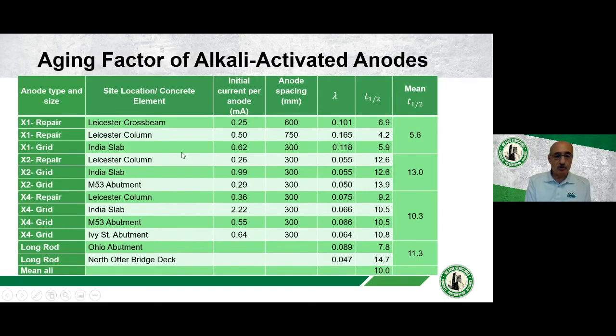Okay, I promised a table before, and this is a whole list of the structures that we have been monitoring, and we've been monitoring long enough, beyond 10 years, so that we could determine what we call the aging factor, or the half-life of each anode. This is the one that I was talking about. It's about 7 years. On the same structure, we had embedded at the same time another area which we've been monitoring, but with a spacing of 750, and you can see that increase in spacing sacrificed the actual half-life. Although the initial current was double, what it suffered from was that it's been diminishing. The diminishing trend was much harsher.